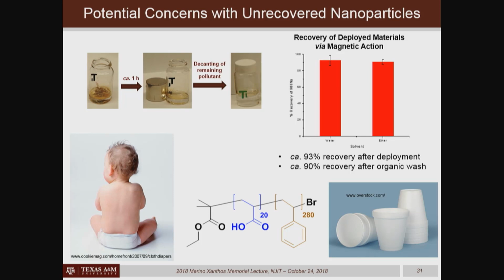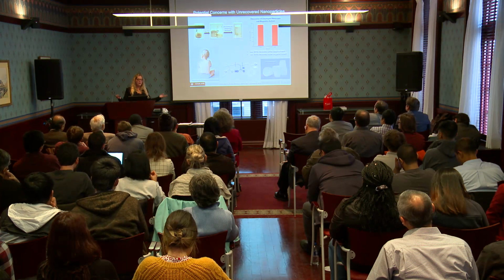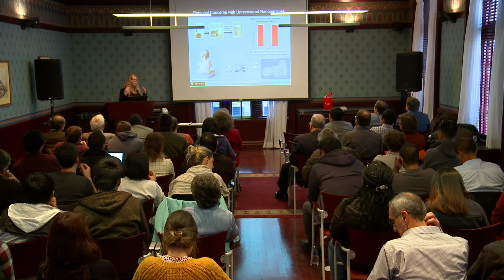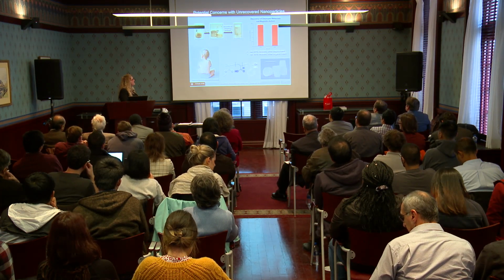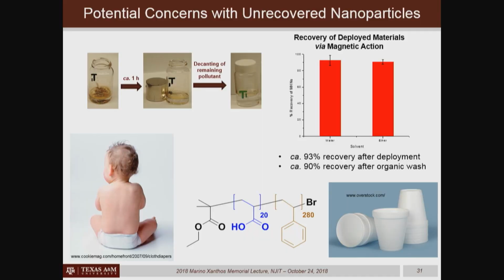Okay, so let me come back to this block polymer structure, because I need to make a full circle back to the nanoparticles for the environmental cleanup. And just say that the work that Kevin had been doing would allow us to get to polymers or cross-linked networks, but in an uncontrolled kind of condensation polymerization. But in order to make well-defined nanoparticles, we need to have this amphiphilic block structure. So we need to have a hydrophilic block and a hydrophobic block connected to each other. And we need to define how long each of those is, because that controls the size and the shape of the assembly that they make when they're put into water.